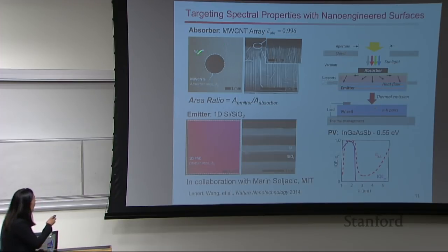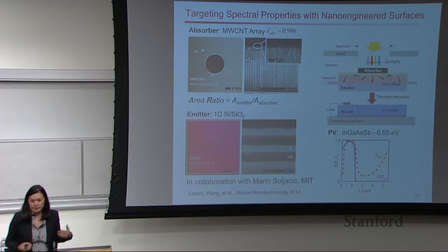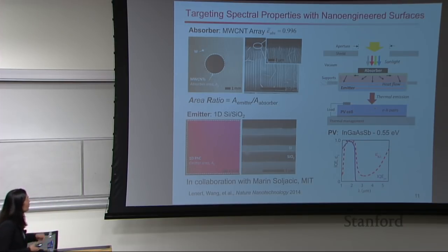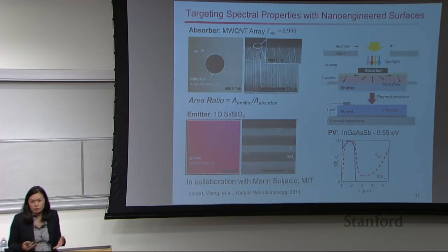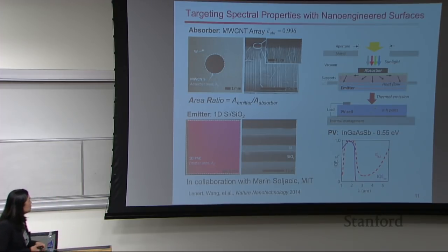And what we've done in the background here is use a low emissivity material, tungsten. Okay, so working with this area ratio and being able to pattern this carbon nanotube array in a selective area, we've been able to get area ratios from about 1 to about 12 using this configuration.